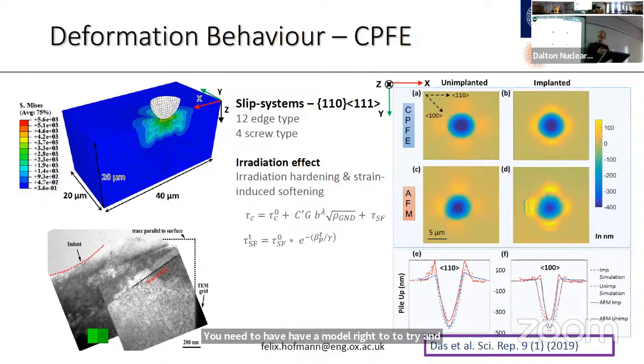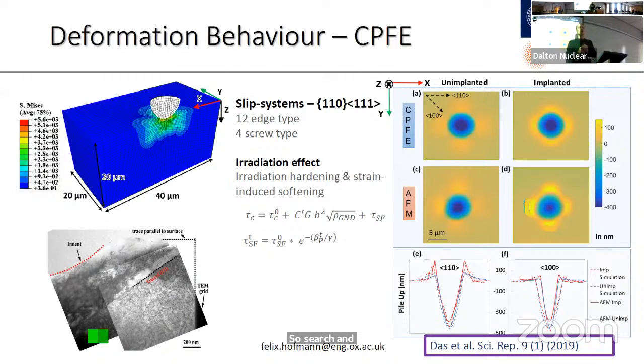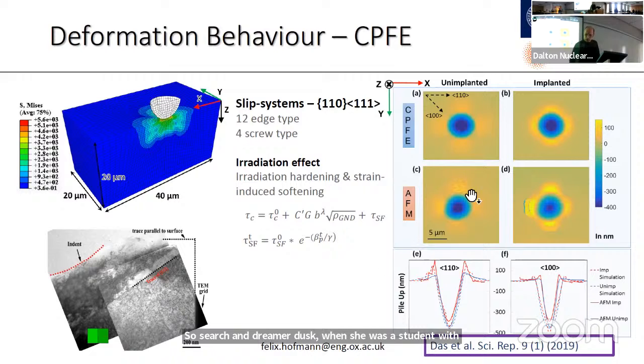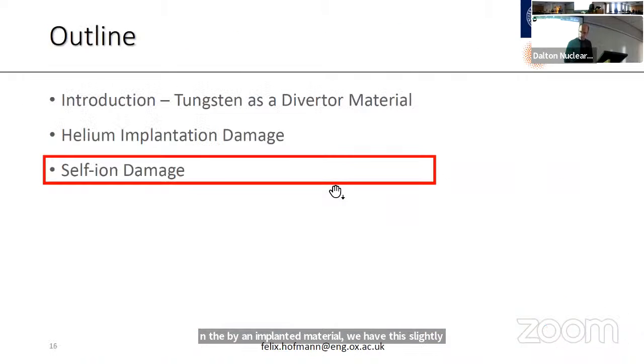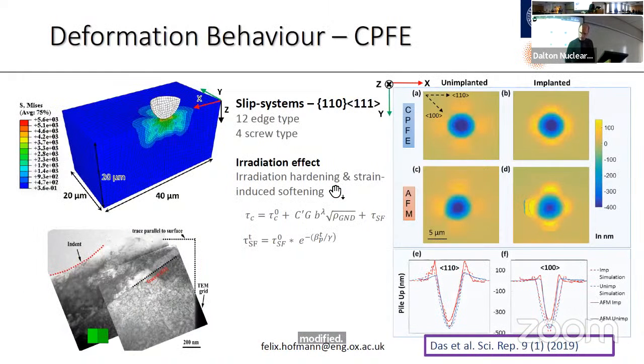So Suchandrima Das, when she was a student with me, built this crystal plasticity finite element model, where you have an indenter, and it indents a block underneath. The top layer of this is ion implanted material, where we have a slightly different constitutive law, and then underneath you have unimplanted material. And in the ion implanted material, we have this slightly modified slip law here. Whoopsie daisy, that wasn't supposed to happen.